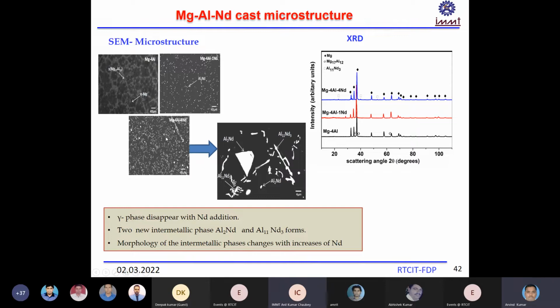And when you are adding neodymium, your gamma phase completely disappears, and two new intermetallics, Al2Nd and Al11Nd3, form. The morphology of the intermetallic changes with increasing neodymium, because it was a point shape, dotted like a dot, and when you are adding more neodymium, the morphology changes into a branch structure and polygonal-type structure.